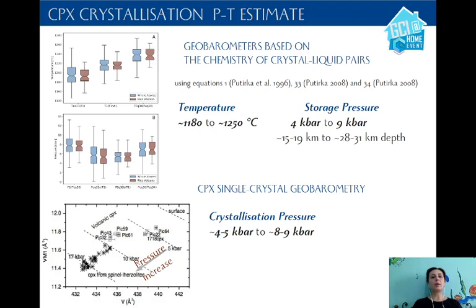Next step was to estimate pressure and temperature of crystallization of clinopyroxene. And to do this, we used two different approaches, one based on the chemistry of the crystal-liquid pairs, and the other one based on the crystal structure of the clinopyroxene by measuring the octahedral volume and the cell volume of our samples. These two approaches converge to the same result, that is that our pyroxenes start to crystallize at 9-8 kilobars up to 4-5 kilobars.